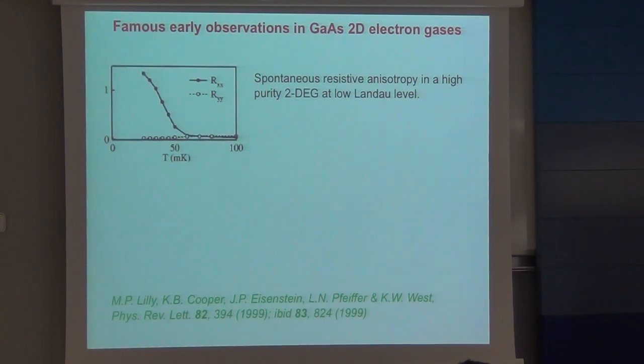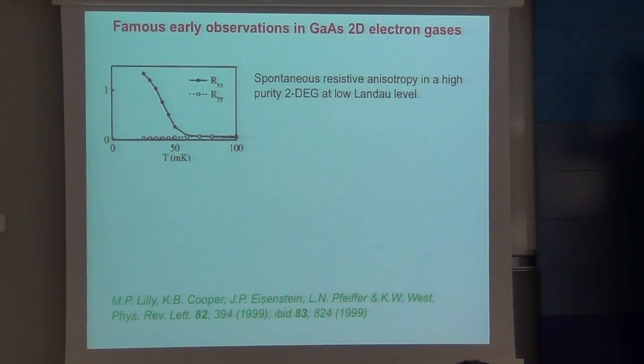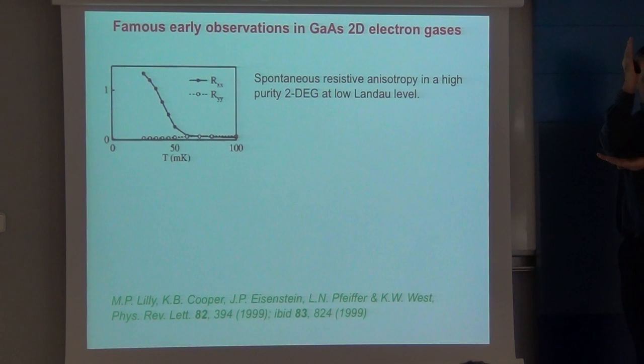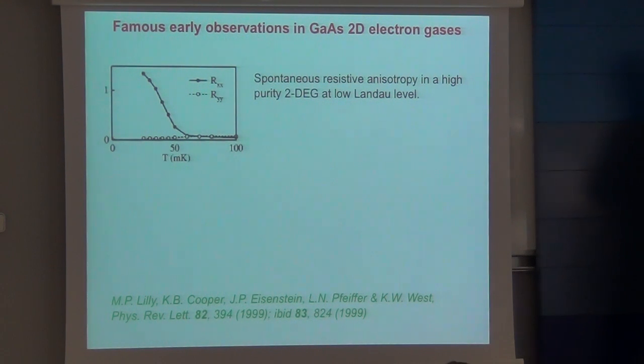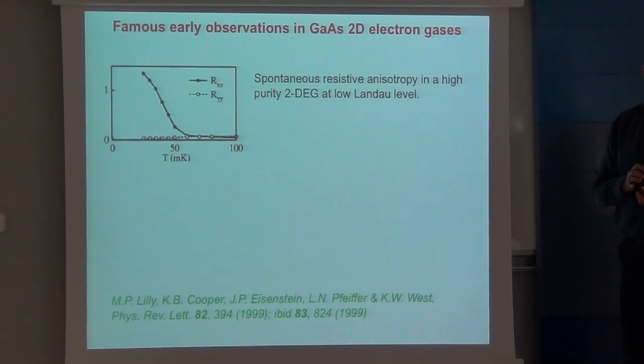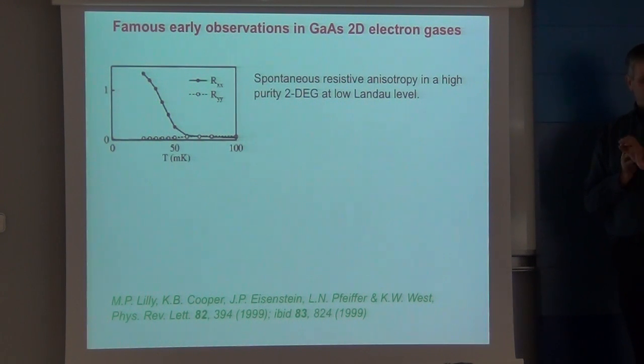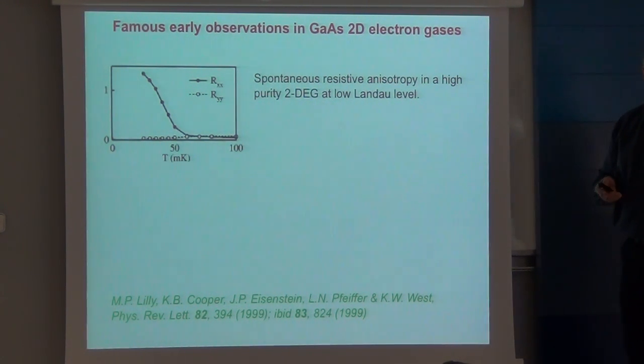Sorry, there is a magnetic field there, right? There's always a magnetic field, so this is in a perpendicular magnetic field. So the magnetic field is perpendicular to the layers, but the anisotropy is lying in the layer, right? And the anisotropy seems to be tuned by some detail of the device, because actually X and Y, one should be favored, but they should always be degenerate. So you always need something to help you choose X over Y. And in these, some details of the device do it. But even in that 2010 review article, Eisenstein's section of that said that they don't fully understand in the devices what's selecting X over Y yet.